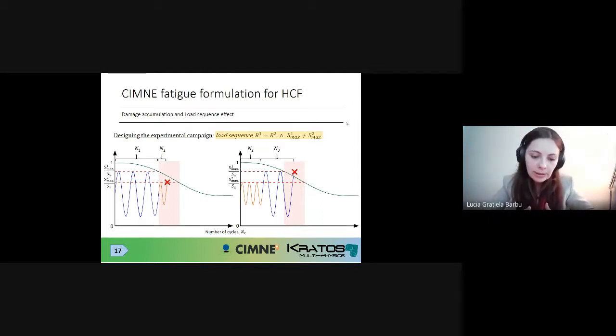It was demonstrated that the sequence in which different cyclic loadings are applied, so if you're in cycle one, or if you're in cycle 2000, or if you're in cycle 200,000, the degradation level is not the same. It can be different. So it's important to have models that are able to account for the load sequence effect and for the damage accumulation. And in this sense, we have been working together with our colleagues at Eurecat, which is a Catalan research center, on designing an experimental campaign that can help us demonstrate that our model is perfectly capable of accounting for this load sequence effect.